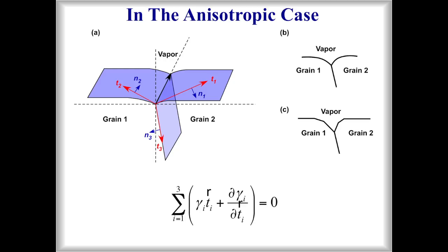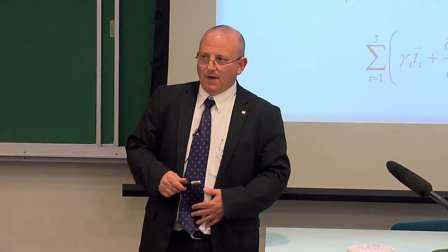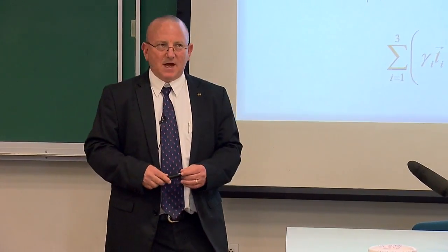We get stuck on solids because solids, as I said before, are not isotropic. And the correct way to write the energy balance at a grain boundary, for example, is the Herring equation, which is written down here, which is this balance of surface energies, gamma, and T is just the vector defining the surface. But there's also this component called the torque, which is the derivative of the surface energy with angle.